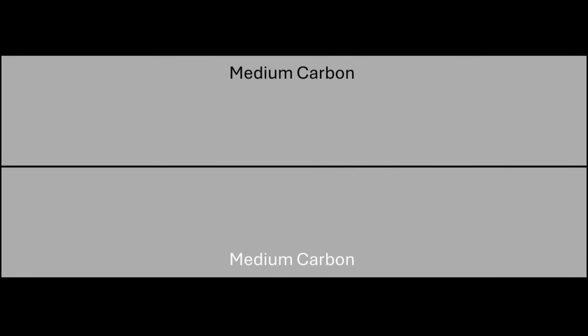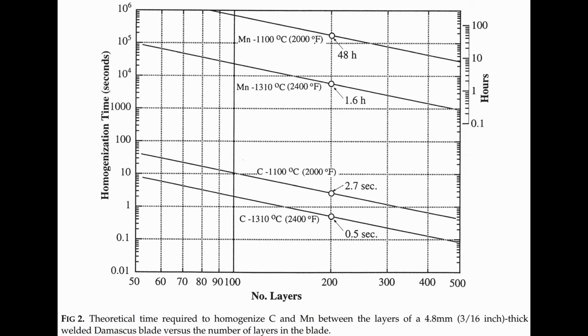And how much diffusion occurs will depend on the temperature and the time and how thick the pieces are. If they're inches thick and they're welded together at one point, then the amount of diffusion that occurs is going to be relatively small in percentage terms. If we have a high layer Damascus, the layers are very small, and so the time for the carbon diffusion is relatively short.